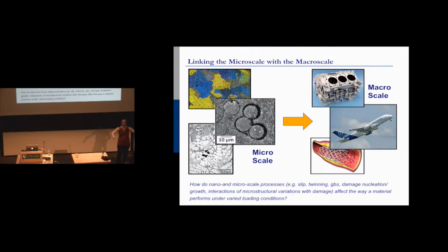Basically we ripped off the door of the SEM and rebuilt a door that was able to port this ultrasonic transducer in. The reason we do that is to look at what type of hotspots we need to avoid. Where did the cracks nucleate? Why did they nucleate there? Statistically, what type of microstructure will cause cracks to appear and to propagate?